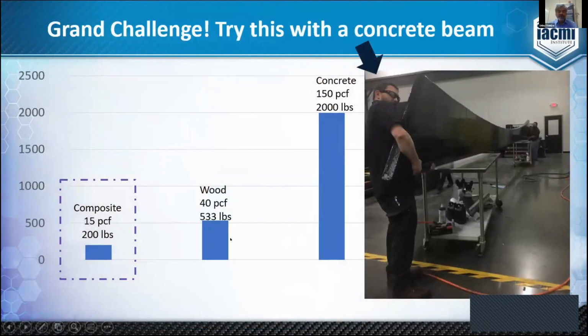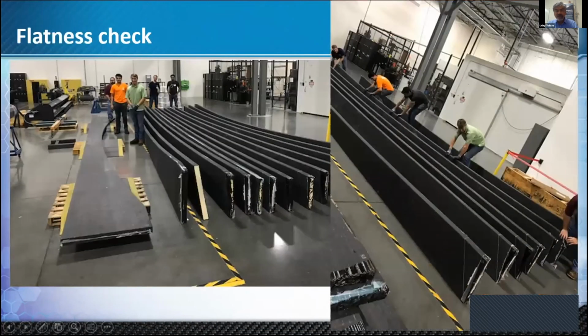The composite beams, about 15 PCF at the end, weigh about 200 pounds. Try doing that in concrete, obviously a huge difference. And if this were made out of wood, it would be about 500 pounds, more than 2.5 times that of the composite beam. All the beams were staged and produced, and all the flatness was checked because the top of these was flat. These are essentially all unfinished at this stage. They had a taper on these sides, so you can see the mark of the taper out here.